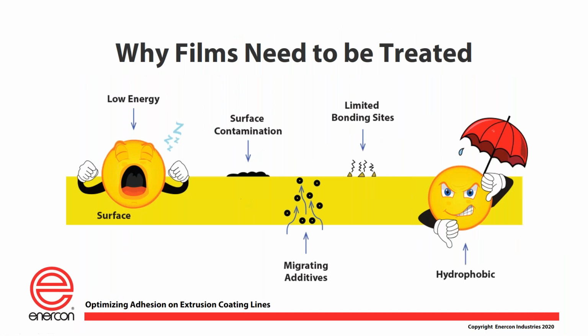So why do we have to treat films anyway? In our last slide, you saw that we have a main unwind and we surface treat it before it goes into the extruder, or for that matter, we now have a product, and before we wind it, we decided, hey, I've got to treat this product before I wind it back up. So why do we have to do that? Well, polyethylene, basically polyfilms in general, whether it's polyethylene, polypropylene, polyester, any of the normal films that you're familiar with, by their nature, they have a very low surface energy. There's really nothing on the surface, no polar groups, no activity, nothing there to allow a coating or an ink or adhesive or something to wet and stick to the surface.